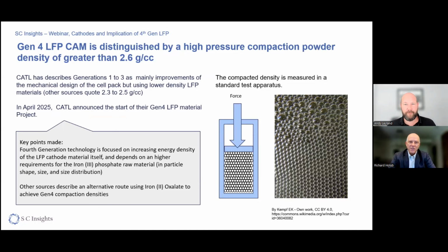The distinguishing characteristic is the high pressure compaction density, greater than 2.6 grams per cc of the powder. This was in April 2025. CATL announced that it was the start of their Gen 4 LFP CAM. That really built on top of the January announcement by the Chinese government of the technology transfer limitations or restrictions. CATL also made a lot of improvements over the years in terms of compaction density, from 2.3 up to 2.5, which are those three grades, 2.3, 2.4, and 2.5, sold in China.